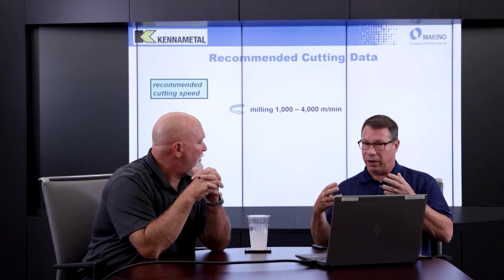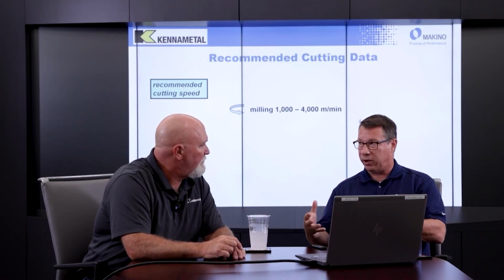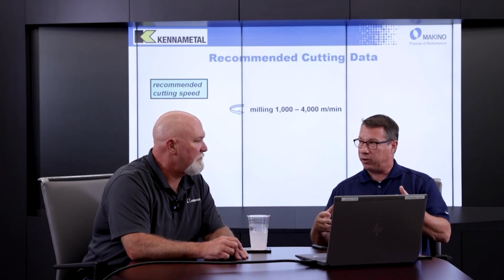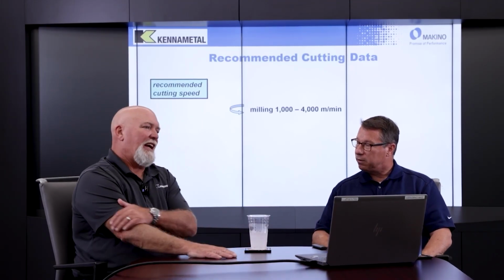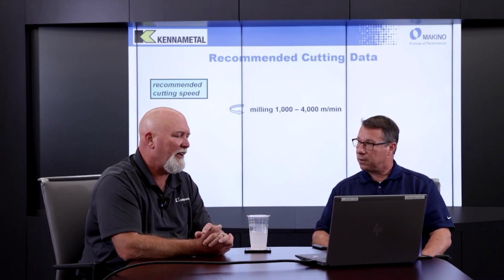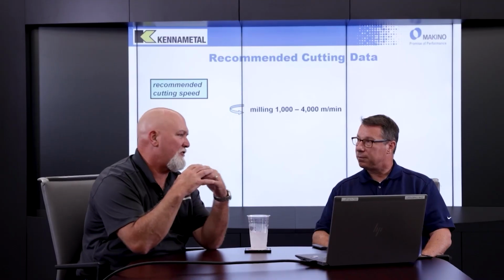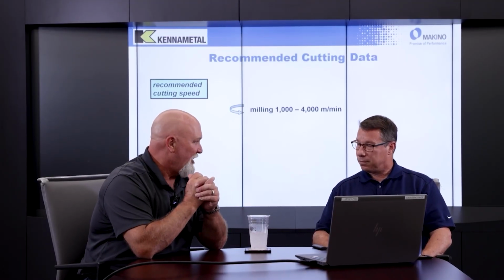One of the things that comes to mind from the standpoint of cubing, in those instances where we still see customers use lost foam casting, any special considerations from the standpoint of that initial milling pass relative to the product that comes out from a lost foam process? Yeah, in fact, I was involved in some lost foam process machining several years ago with General Motors, and the lost foam process leaves a scale on the outside of that material because there's a ceramic that gets impregnated in there, and it becomes very difficult to machine in the cubing sense.